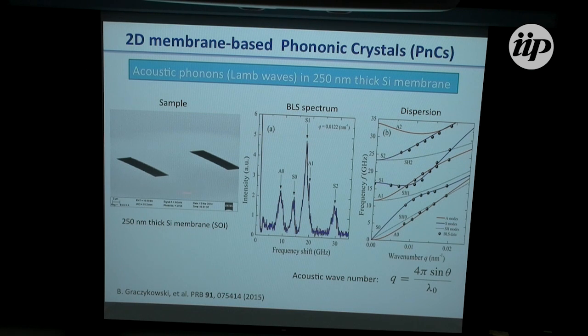We characterize the membranes by inelastic light scattering, Brillouin scattering, and that gives us a peak into the resonances in the material up to about 30, 40 gigahertz, with very clear peaks that can be plotted on a dispersion relation curve. This is a calculation. We use COMSOL for these type of things.